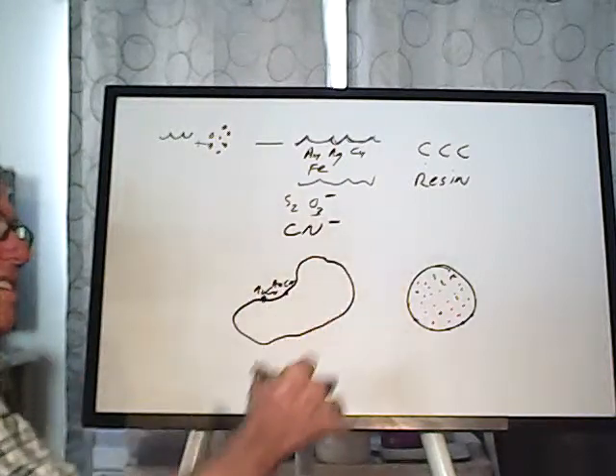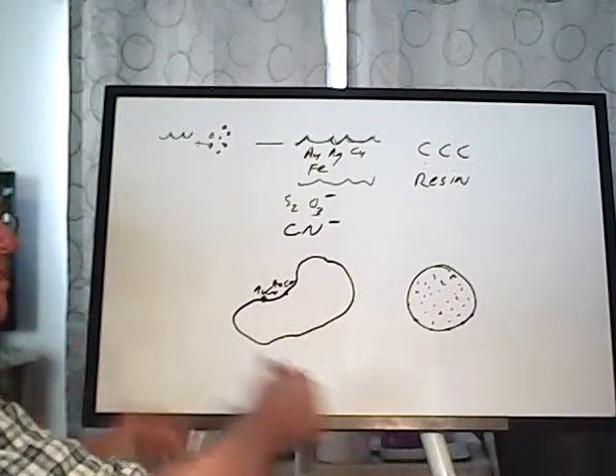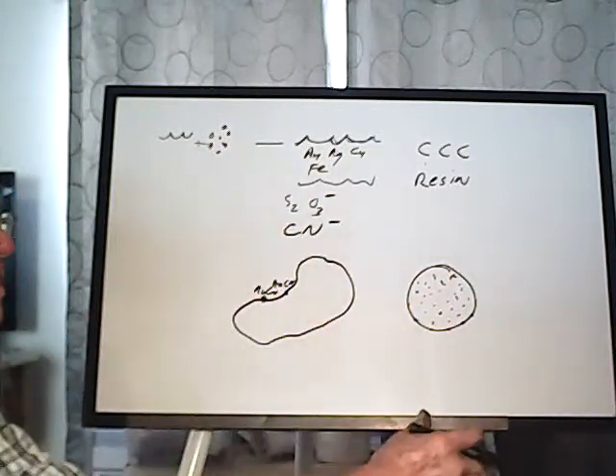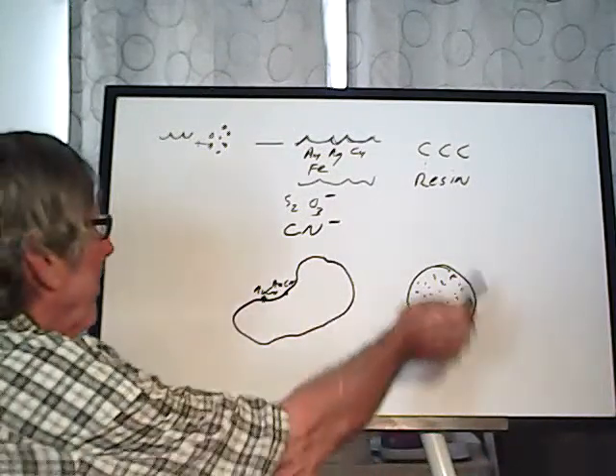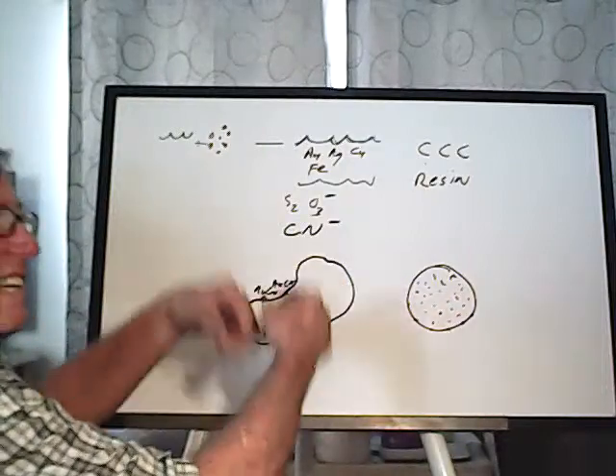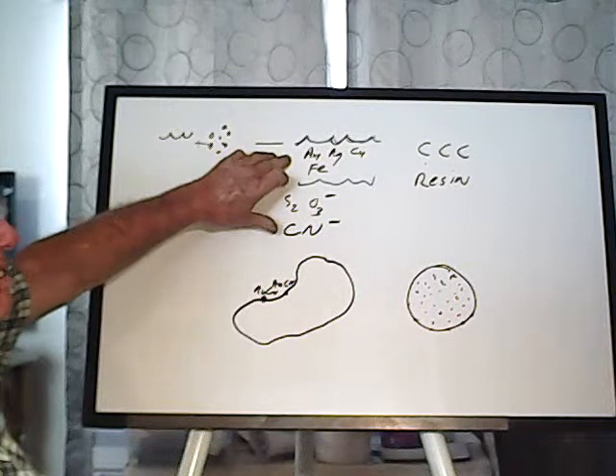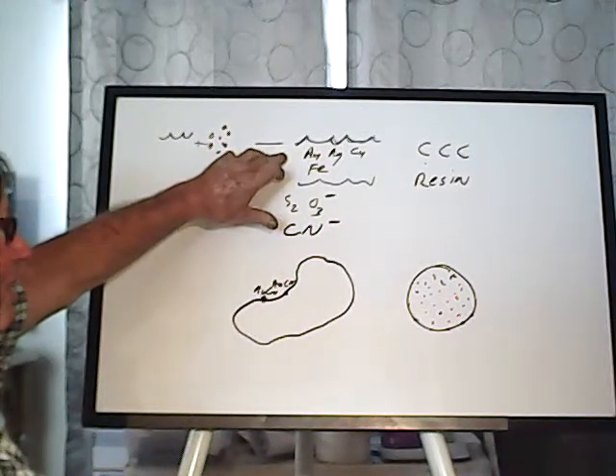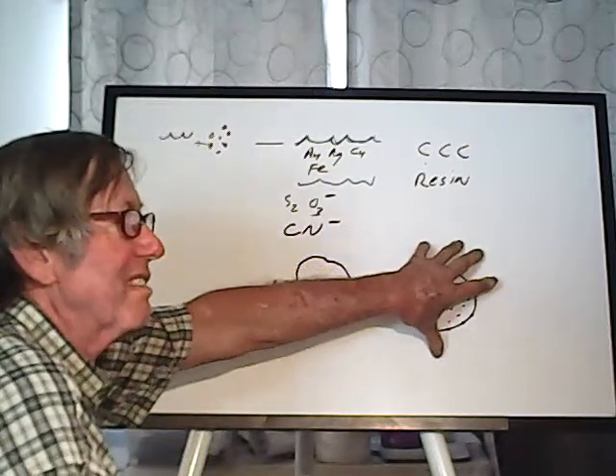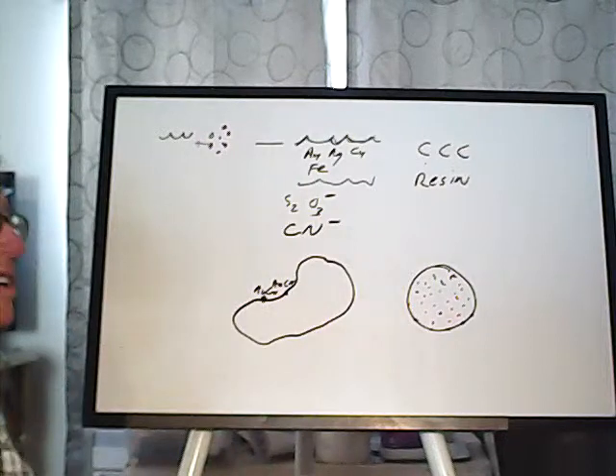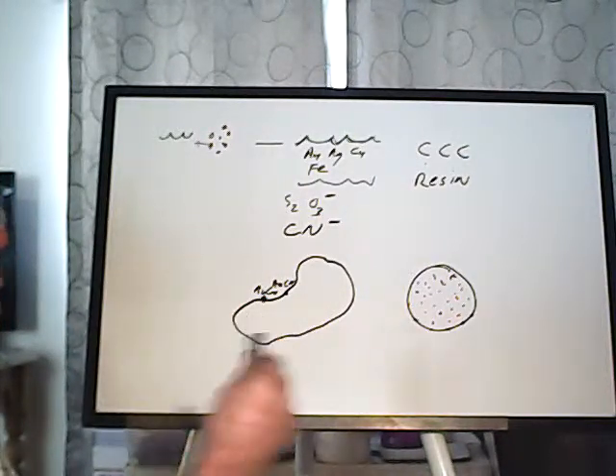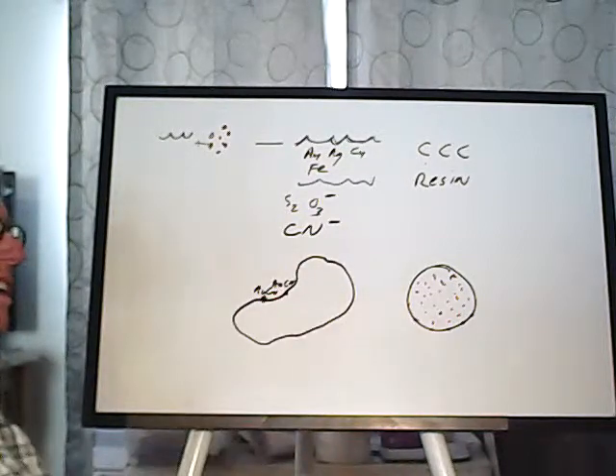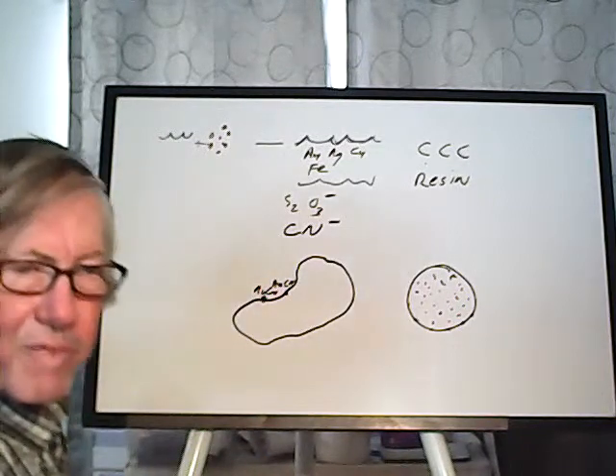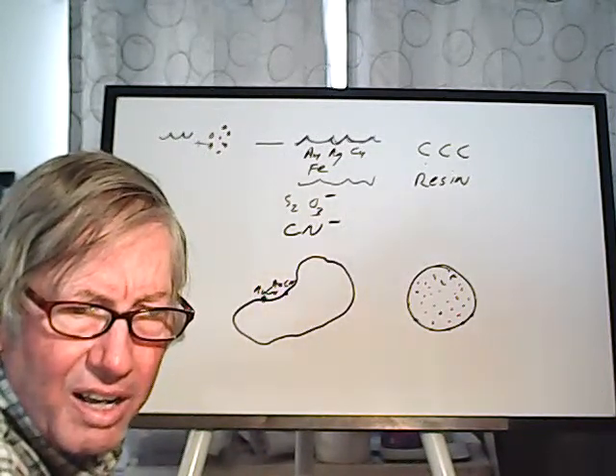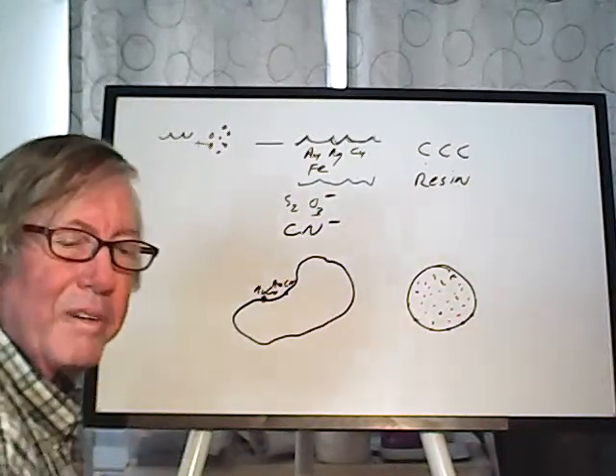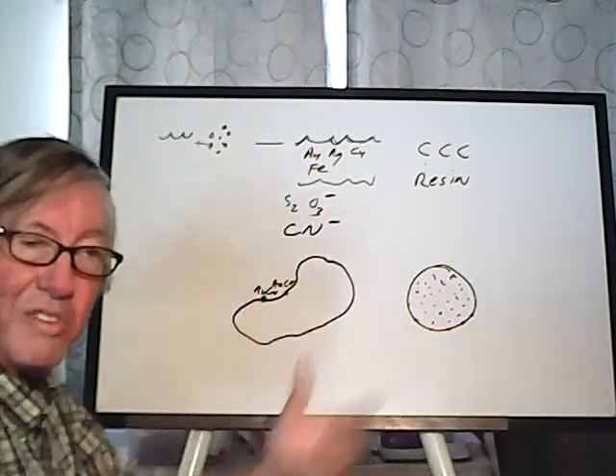So to get it back out, you use a flush with one set of chemicals to try and get the other crap out first. Then you do it to get the gold out. Once it's absorbed, you have to do something else to get it back into solution. Whereas this initial solution may have had a very, very low concentration of gold, when you elute or desorb this, you can get a much more concentrated solution, which is then much more suitable for things like precipitation or electrowinning, electroplating. It's the chemical makeup and the surface area. That's why it tends to come in small beads to improve the surface area.